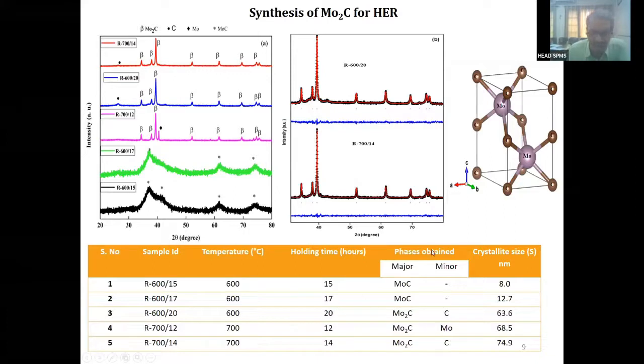So these are the phases present inside the material. One can see that the major phase is molybdenum carbide, which exists in two forms. One is MoC, another is Mo2C. Our interest is not in MoC because MoC is not a good catalyst. Mo2C is a very good catalyst here. So after optimizing the process parameters, you can see that for the material synthesized at 700 degrees centigrade with a holding time of 14 hours, we are able to get the Mo2C phase along with the carbon.